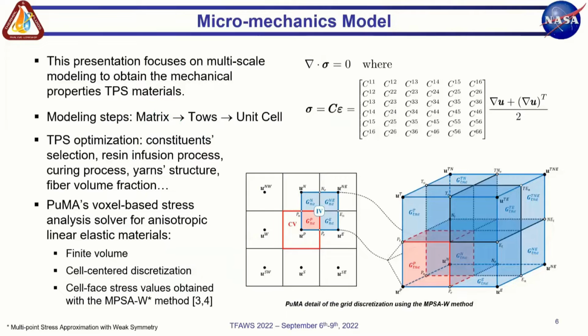As I said, with PUMA, we focus on multi-scale modeling to obtain the mechanical properties, and specifically there are 3 scale levels or modeling steps for a composite TPS material. The first step is modeling the matrix at the smallest scale, and then we can model the tows or yarns that form the structure of the material. And after getting the results for both of these constituents, we are able to model the unit cell. This multi-scale modeling process allows for TPS optimization by, for example, changing the resin infusion process, the constituent selection, the tows structure, and so on.